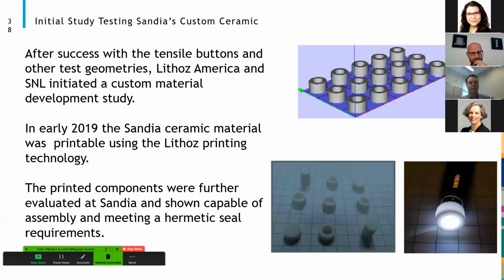After success with the tensile buttons, we looked at other geometries that were critical for our components here at Sandia. In 2019, we engaged Sandia to develop our ceramic material within their slurry and print some components that meet our requirements as far as shape. The printed components were printed using our slurry, or our ceramic, and brought back to Sandia for evaluation. The evaluations determined that not only did they meet the vacuum hermetic seal requirement, but they also were capable of meeting a dissimilar braze.